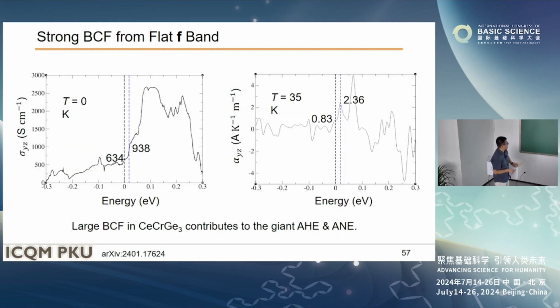And we also calculated the Berry curvature field in cerium, and we see the number is close. Of course, you don't expect a very precise calculation because strongly correlated systems are difficult. But anyway, it can be some indication. For lanthanum, I didn't show it here, but the number is below 100, so it's consistent with our measurement.